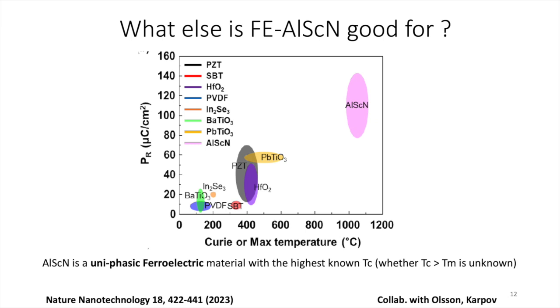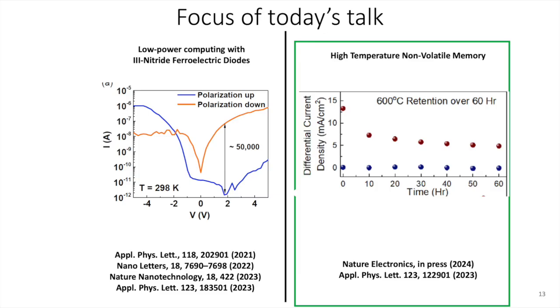They did it in very, very thick material, so it's not really a device. They took a large, thick crystal of the material. They polarized it electrically. Then they put it in a furnace for a certain number of hours at 1100 degrees Celsius, took it out, and again measured the polarization. Right? That's a good, neat proof of concept, but you actually have to make integratable devices that can work. This is something that we went in and developed, and we are also hoping to commercialize them in the months and years to come. So going to the next slide, this basically brings me to the topic of high temperature non-volatile memory, why it is useful and why we are trying to make it using ferroelectric aluminum scandium nitride.